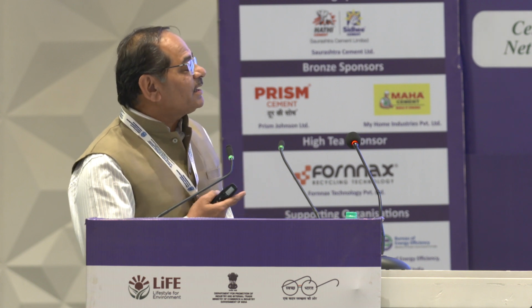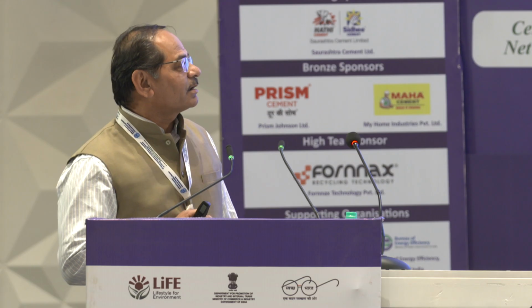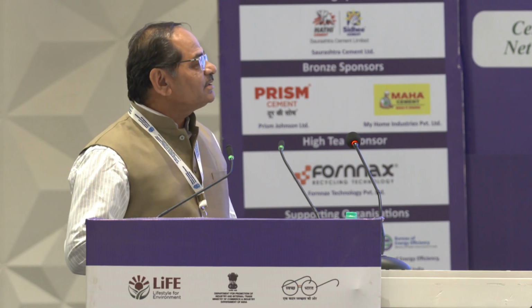So the solution adopted and action implemented by the plant is the usage of red mud. Red mud is itself a waste of the aluminum industries. Until some time before, red mud disposal was itself a big issue, but now it is being used in cement plants. This red mud has iron percentage, which can replace one corrective material known as red ochre. Along with that, it has a higher percentage of Na2O, the alkalis, that help in the alkali sulfur ratio we saw. So it mitigates some ill effect of the sulfur, and it helps to remove the sulfur from the circuits.